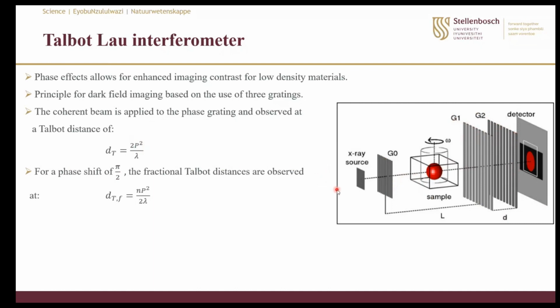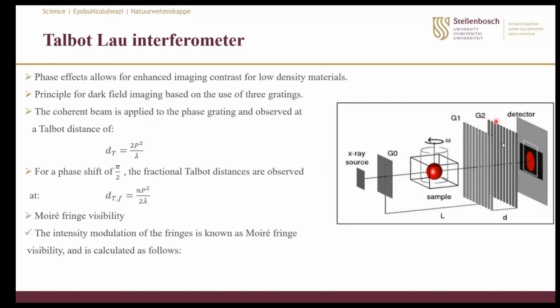So after the setting has been done and the distance between the gratings is kept at minimum, what we will see on the detector over here is what we call moire fringe. Moire fringe visibility is actually the intensity modulation of the fringe, and it is measured by taking the ratio of the difference between the maximum intensity and the minimum intensity.